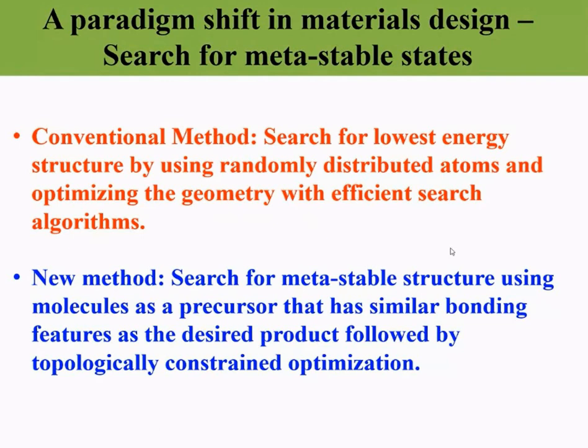As a matter of fact, if you look at one of these hexagons, and you look at the 2 carbon atoms at the center, you rotate that carbon dimer by 90 degrees and you get exactly pentagraphene. And the energy barrier to rotate is essentially negligible. So once you form this structure, one can simply transform into a pentagraphene.